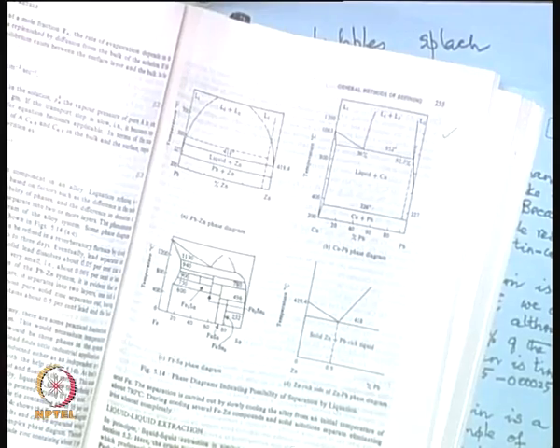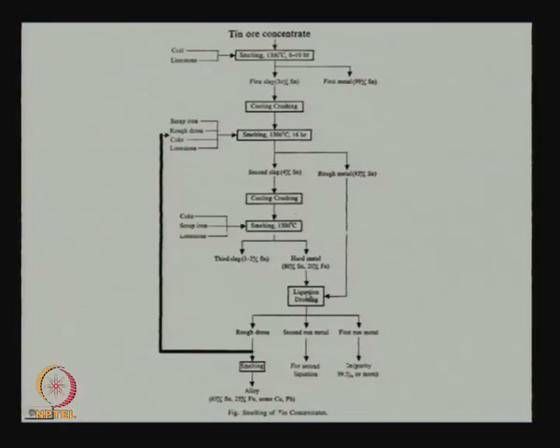This is what is done by liquation, that you simply take that alloy which contains iron and tin, take it to a temperature of about 600 or so, and it will have two layers now. Tin will float up because it is lighter than the iron-tin alloy. That iron-tin alloy has only a small amount of tin, but what is floating up is almost pure tin, that can be taken out. So, these are the principles of liquation. That is what will be done in liquation drossing. Liquation drossing means constantly you get something floating up and you remove it.